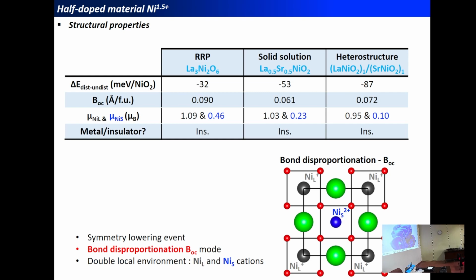And if we perform the structural relaxation in all the 3 systems, we see that we have a very large energy lowering with respect to the undistorted cell, and this energy lowering is associated with the appearance in the system of a breathing distortion, producing this time not compressed octahedra and extended octahedra, but extended O4 groups surrounded by compressed O4 groups with a rock salt pattern.